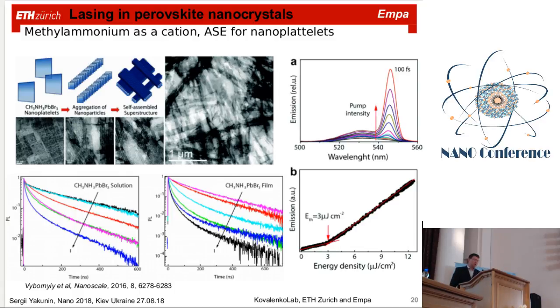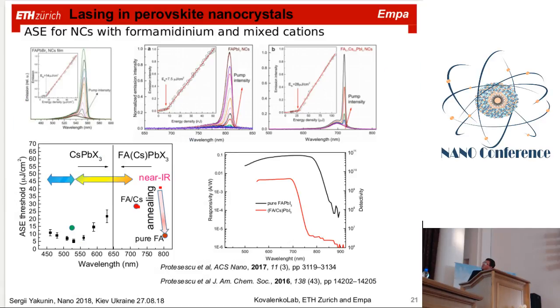Then we were interested in working with another type of cation, again an organic ion, formamidinium, which in certain cases provides better chemical and morphological stability. And we also demonstrated that this material shows optical gain for green emission when the anion is bromide. We also worked quite a lot with iodides, which make the narrowest band gap possible for those perovskites.